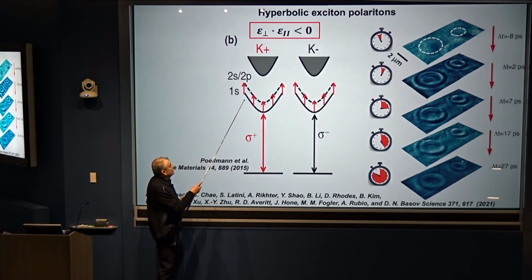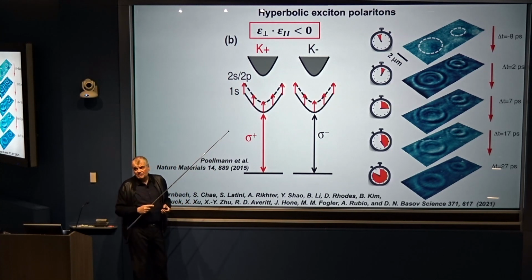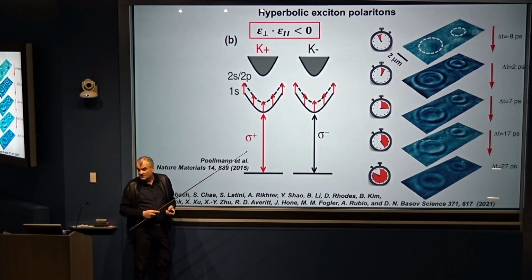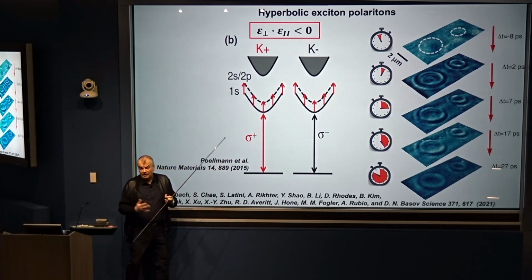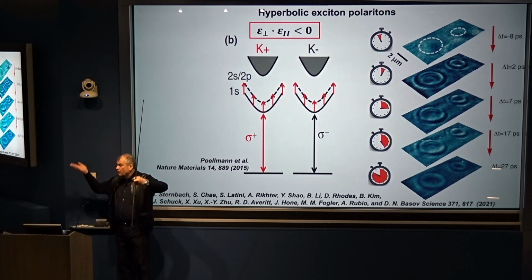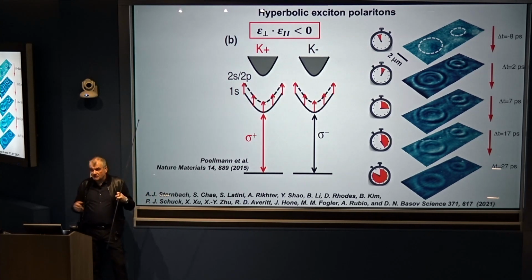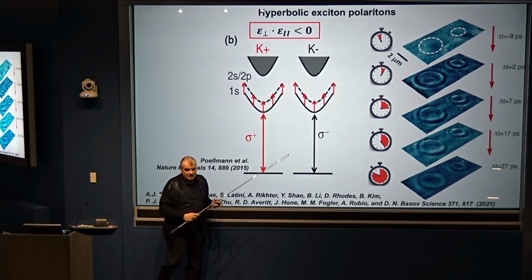These crystals support very intense transitions, sometimes referred to as Rydberg transitions, in parallel to atomic physics. They have incredible oscillator strength, but they're dormant at equilibrium. So in order to get access to this transition, you have to photo-excite your crystal first. That's the purpose of this pump in this experiment. Once we've populated one state, then we can take advantage of hyperbolicity associated with these inter-exciton transitions.